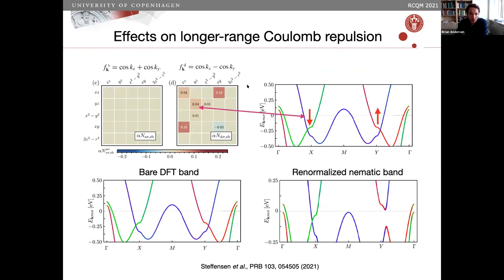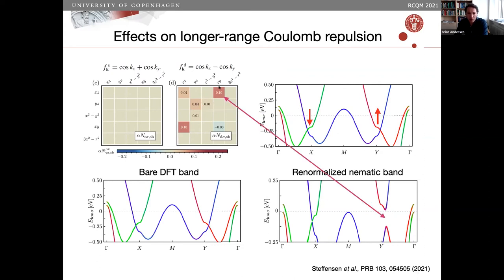Looking now in the symmetry-breaking channel: there is no s-component but there is a d-component, and there's a lot of structure here. This is nematicity arising from the nearest-neighbor Coulomb in the realistic five-orbital model, in the d-channel. First, there's an asymmetry — the form factor gives a sign change, so there's a small shifting up and down of electron pockets from nematicity. However, the largest component is this inter-orbital component connecting d_{xz} and d_{xy}. In another domain it would be d_{xz} and d_{yz}, but this is exactly what causes the gap to open up at the Y-point, hybridizing these two bands. If this is large enough it can actually lift this pocket above the Fermi surface — generically this inter-orbital component is the largest component found.